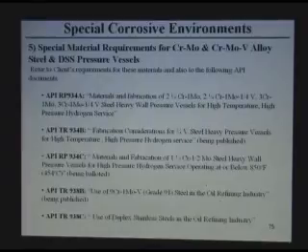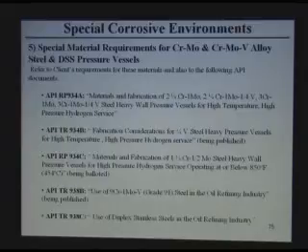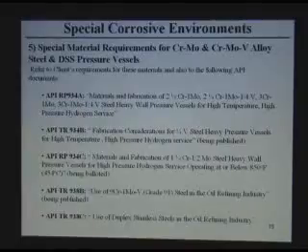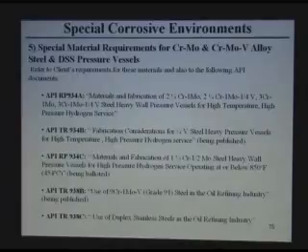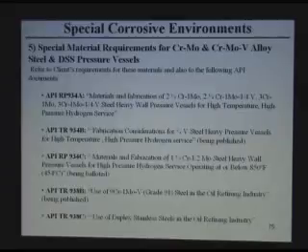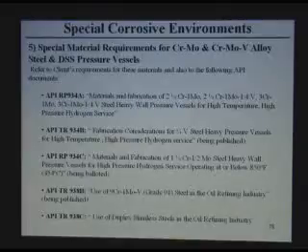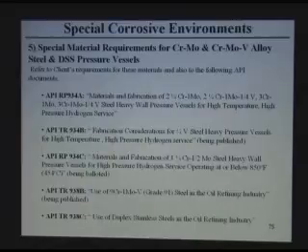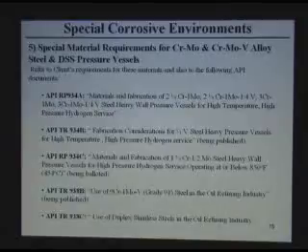When you go to hydrocrackers and hydrotreaters, you have to use heavy wall type reactors, as we are doing in the Chevron job at El Segundo, I think. We use chrome moly and chrome moly vanadium alloy steels for pressure vessels, and there are API documents that give the requirements for these steels, especially for heavy wall reactors. Because, as I mentioned before, chrome moly tends to have temper embrittlement, which means the steel becomes brittle after some time. We don't want the high-pressure equipment to fail due to embrittlement. So this document, API 934, gives you requirements for heavy wall type reactors made from these materials.